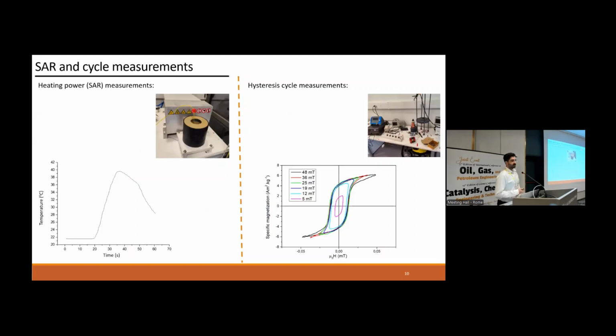In order to study our iron wool and to determine how much it heats and the mechanisms that are taking place, we have mainly two types of experiments. The first is the classical thermometric measurement, where we would apply magnetic waves onto our samples for a set time period. We would measure the temperature increase, and then, of course, we can measure the amount of heat that's being created. And we would so calculate something that we call the SAR, which is specific absorption rate for a material, and it's watts per gram of iron.